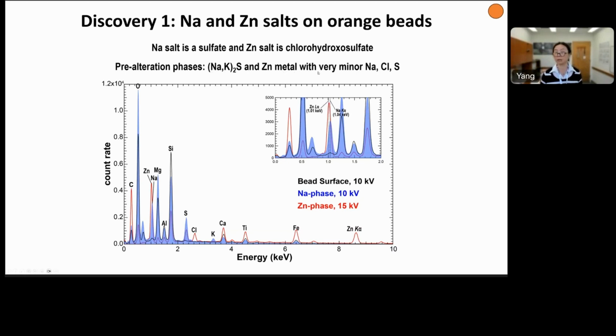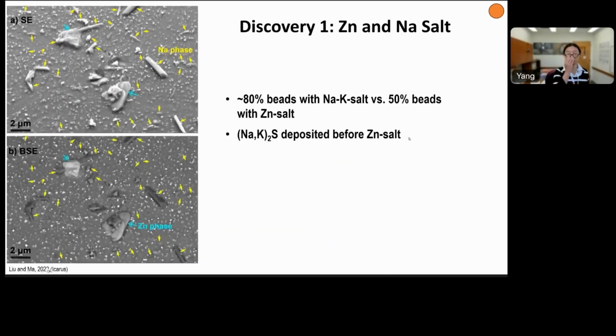Even if we assign all sodium to chlorine or sulfur, and zinc to chlorine and sulfur, there is excess zinc that can only be explained as zinc metal. Also, from the SEM observation, we can look at the texture between the sodium and the zinc salt. From the images shown here, as you can see, the zinc salt lies on top of the sodium one, which suggests the sodium sulfide was deposited first before the zinc formed.